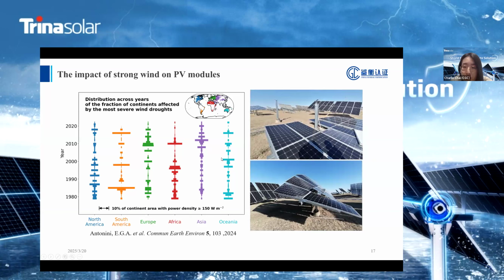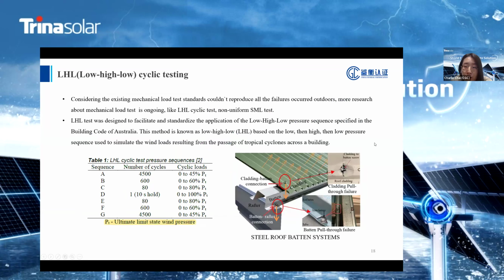The right picture is a region in Inner Mongolia, which suffered continuous gale force winds, with an average wind force of 8 to 9 and a maximum wind force reaching 11, causing tracker breakdown, frame deformation, and glass cracking. Considering the existing mechanical load test standards couldn't reproduce all the failures occurred outdoors, more research about mechanical load tests is ongoing, like low-high-low cycling test, non-uniform static mechanical load test.